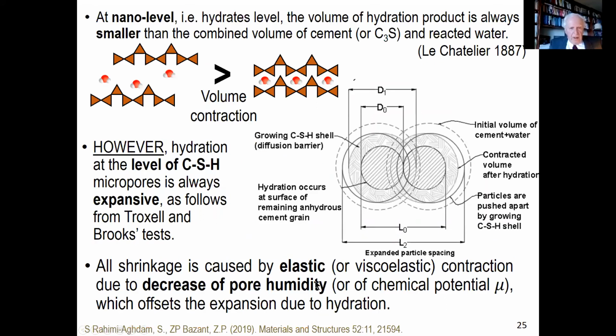All right. So now, what does it mean? How does this expansion happen and why? So you have particles forming, and we start with a grain, which eventually grows. The CSH grows to two spheres in contact, and when they want to grow more, they cannot because they overlap. You see overlap of these two circles. So what happens? But there is a structure. These particles are not free to move. They are part of a skeleton already. There are other particles. So it is resisted.